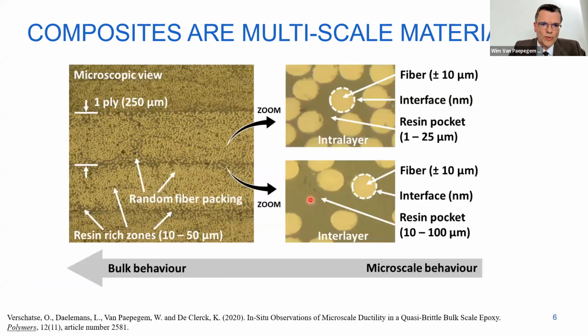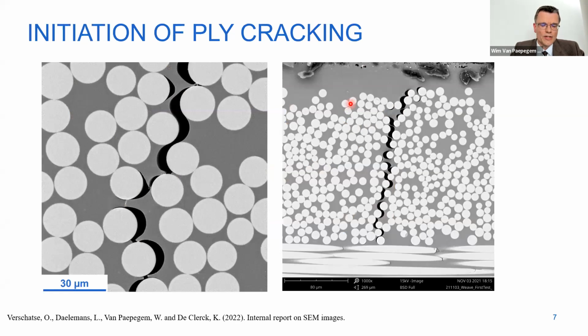First, just still a few things more to give you a bit orders of magnitude. If we have such different layers in a composite, one ply is typically a few hundred micron or even less if it's prepreg. And if we zoom in, we indeed have these individual fibers, roughly 10 micron in average diameter, polymer around it. And then this interface will also come back in my presentation, a sort of nanometer sized interface between the fiber and the polymer, which has to make sure that they adhere well together. And then about damage, this also has this multi-scale nature.